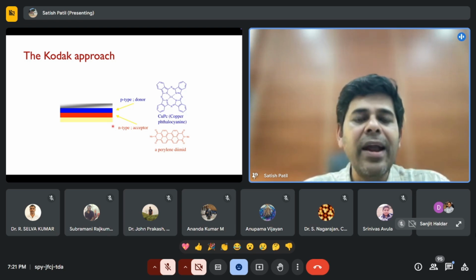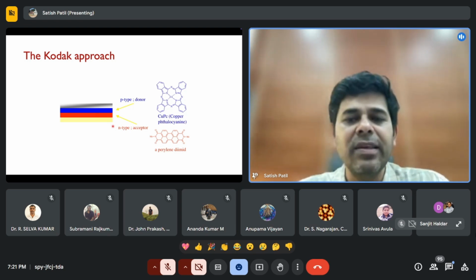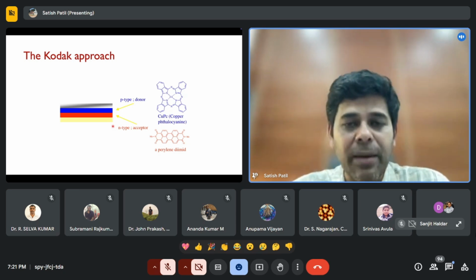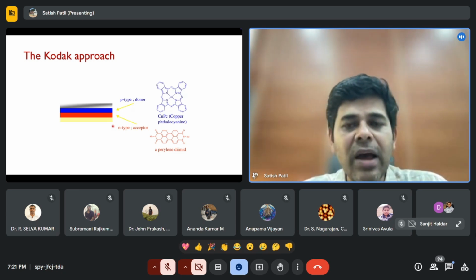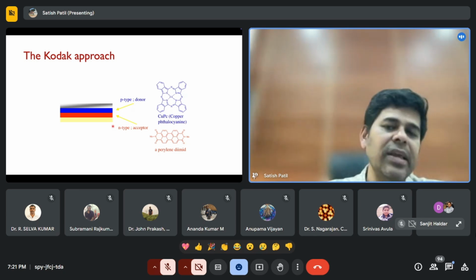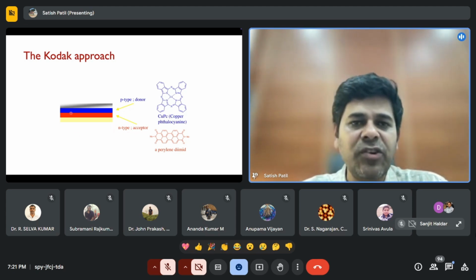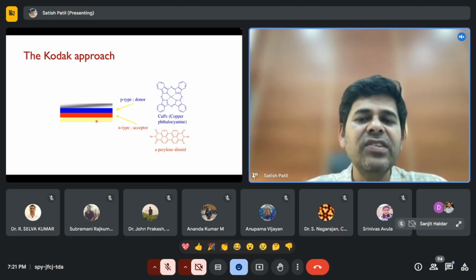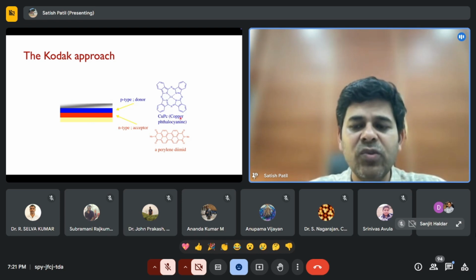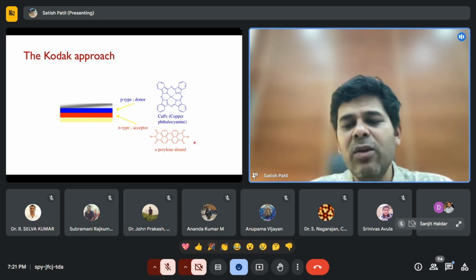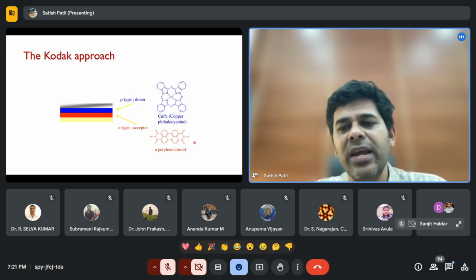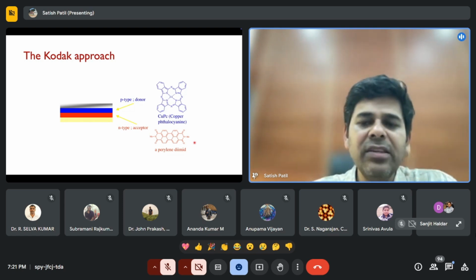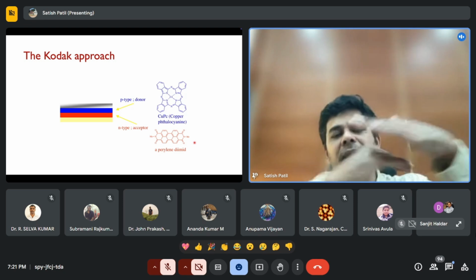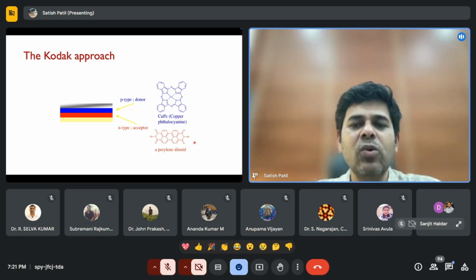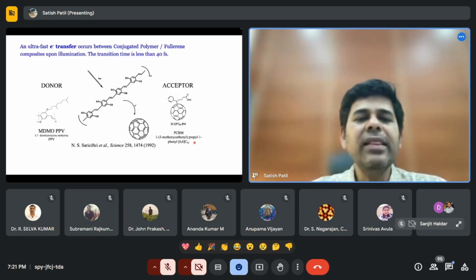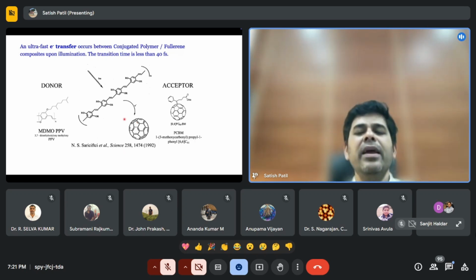And indeed, the idea is to show that organic semiconductors work in photovoltaic applications. So these materials are not as good as silicon, but conceptually, this is the first time Kodak used these semiconductors. Very simple. Perylene diimide, you can make in kilograms. Copper phthalocyanine is a P-type. Perylene diimide is an N-type, and you can make a separate layer of these two, put electrodes, and it worked. But then this is a very important paper, which came in 1992.